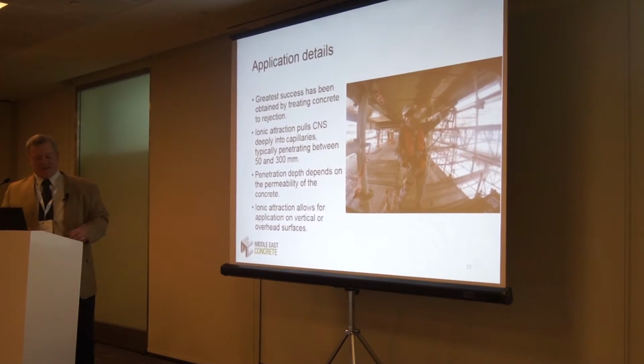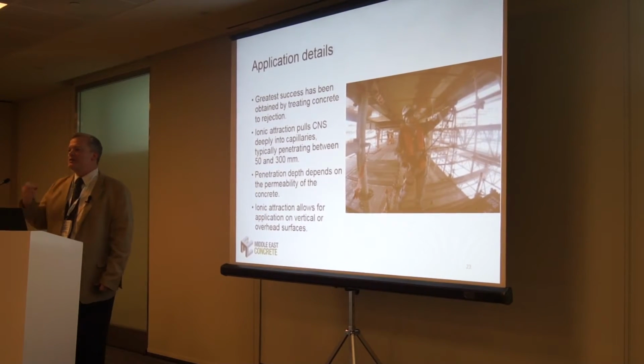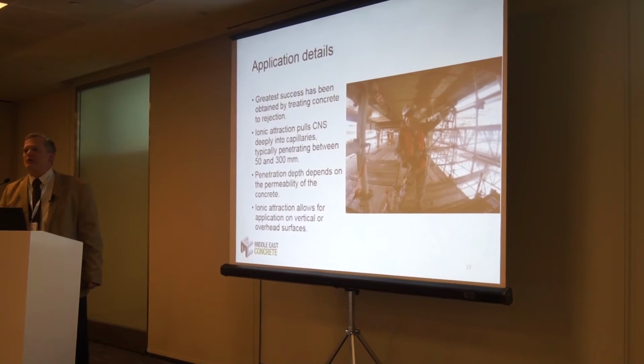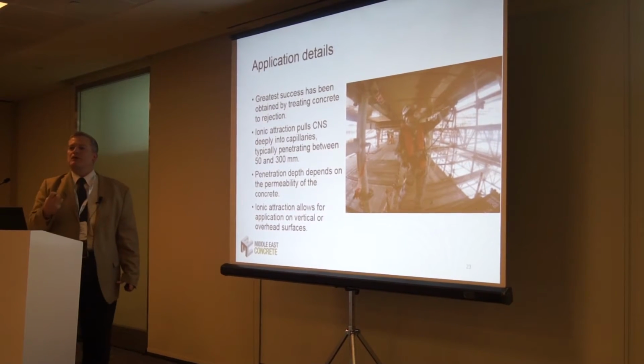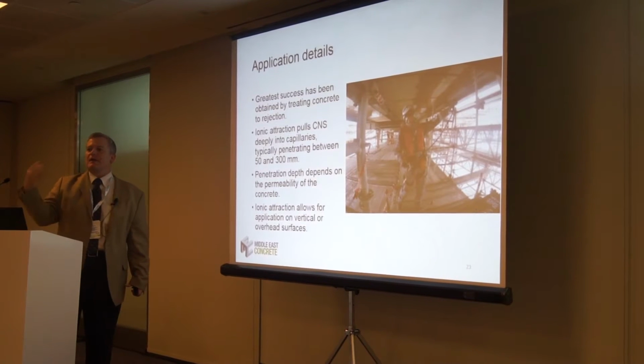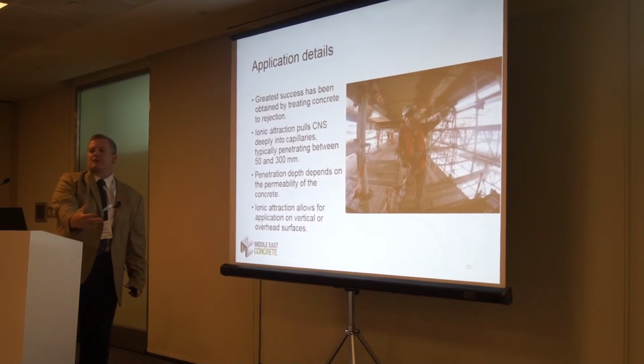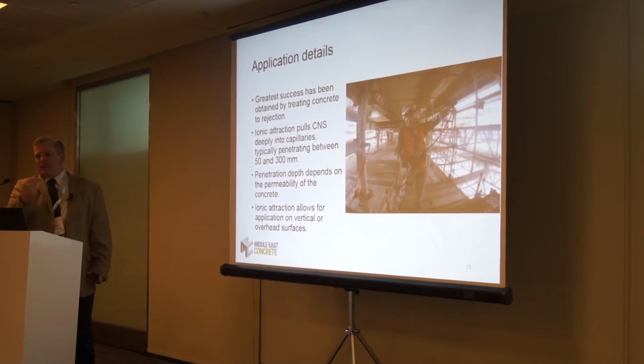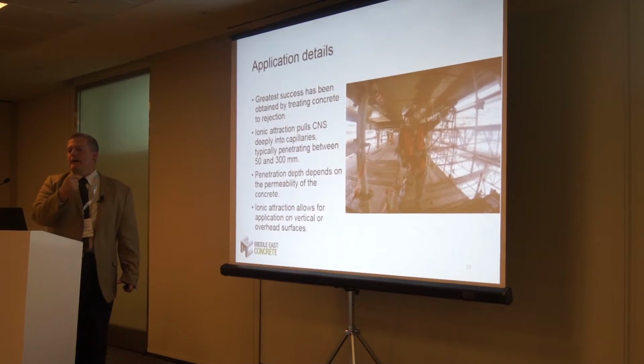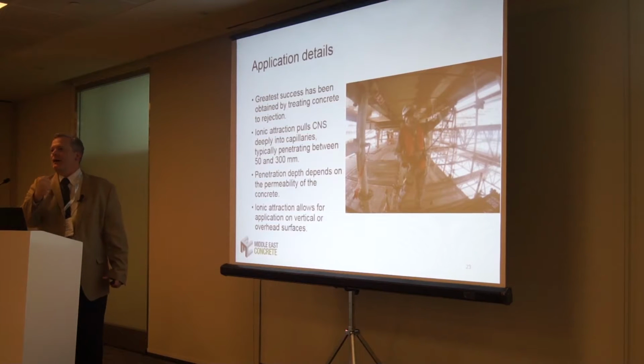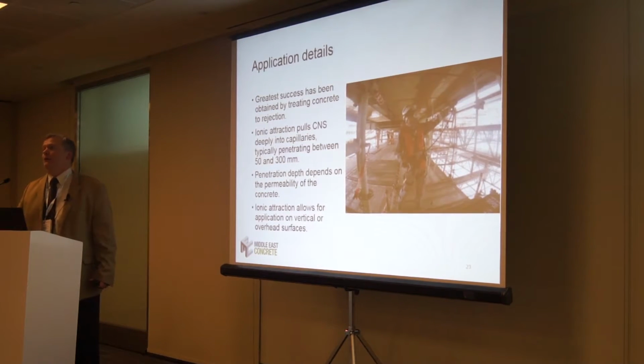So, but yeah, we've actually seen it displace things in the capillary void structure. It's preferred because of that ionic attraction. It gets pulled into those capillary voids. The reaction begins to happen, and it's making calcium silicate hydrate. And as it makes that calcium silicate hydrate, it's pushing anything else that's in that void system out.